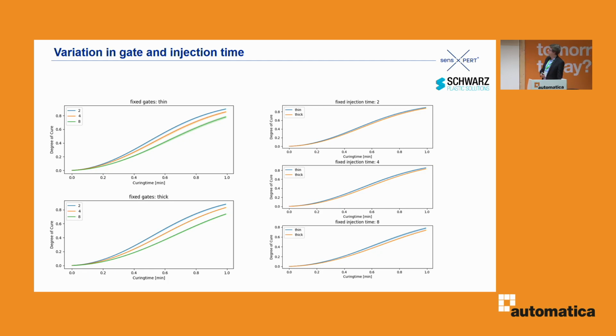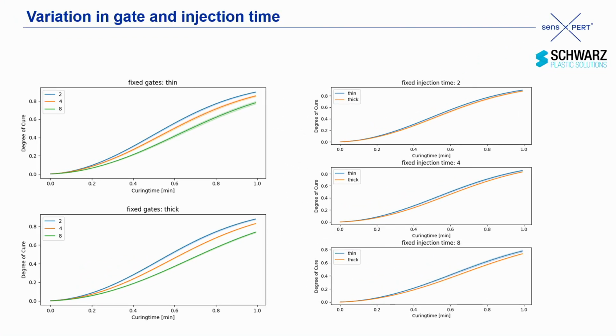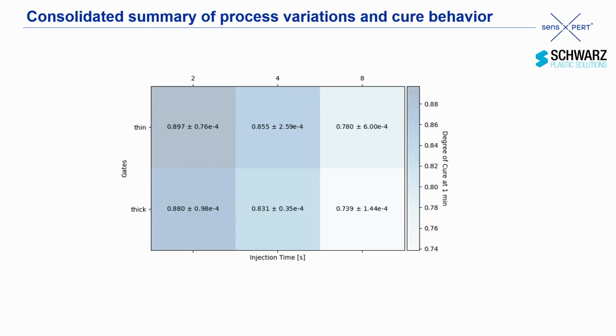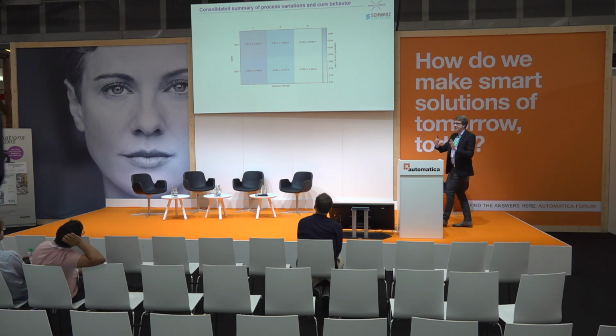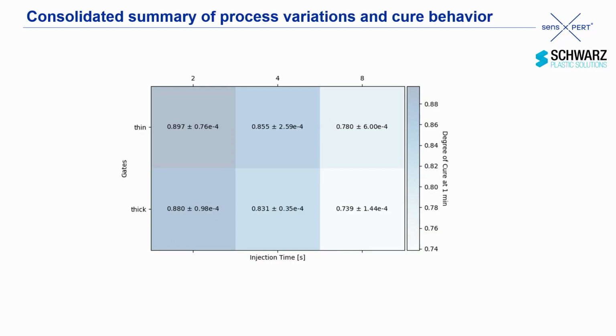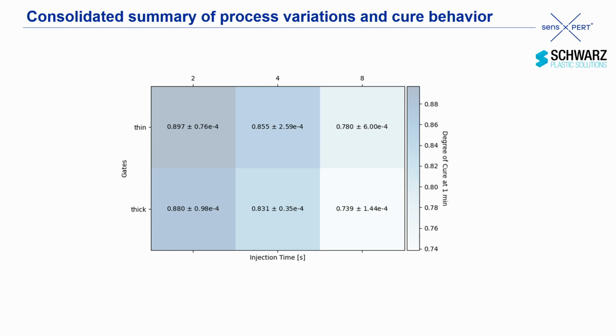Besides the injection velocity, it's also depending on your flow path. So the little channels that the material needs to flow through, are those thick, are those thin? If they are really thin, again, shear is higher and the reaction is going to kick in faster. As you can see here, for example. So in the thin channel, everything is shifted a little bit to earlier times. And so as expected, if we have a very thin flow channel and fast injection speed, the degree of cure, if we have a fixed cycle time, fixed processing time for the machine, we are going to reach a higher degree of cure. More chemical reaction has happened up to that time. That is expected behavior, but here we have now a means to quantify this and control our machine based on that information.